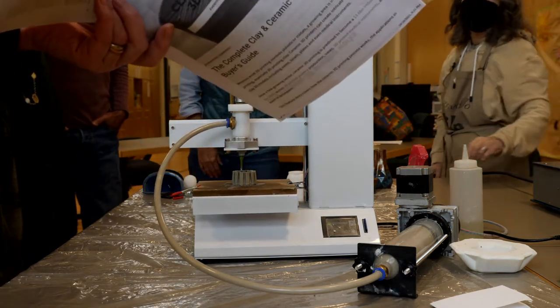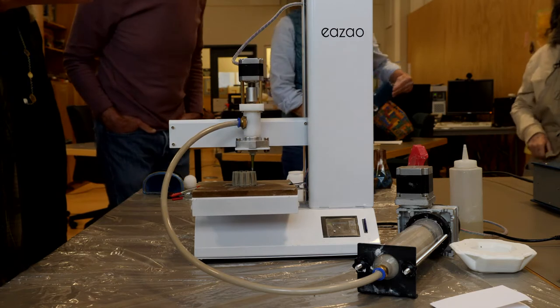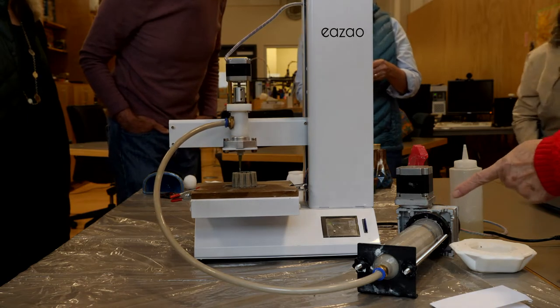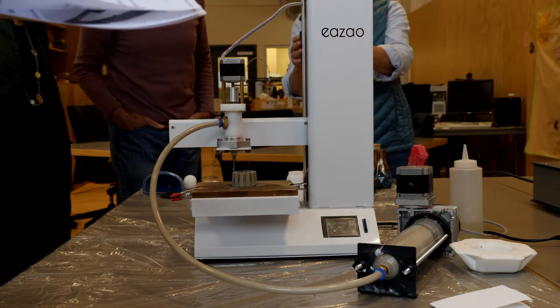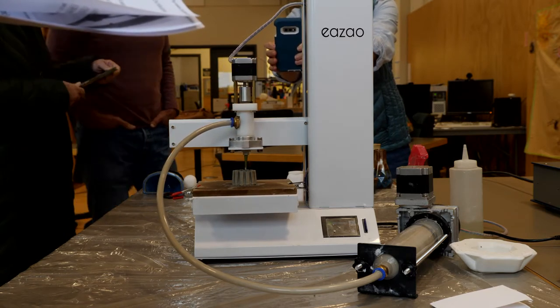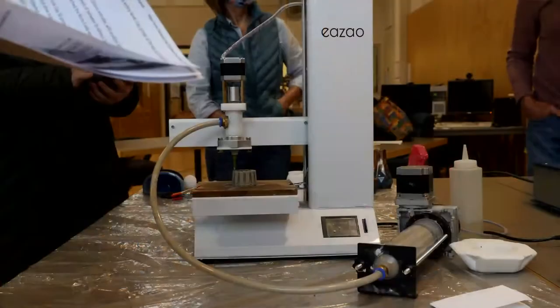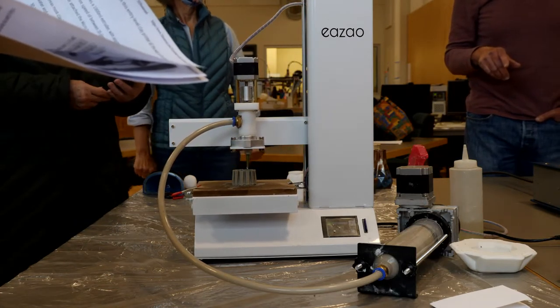So is this porcelain that you're extruding here? That is not porcelain. It's just stoneware. It's the most plastic stoneware they have. I can't remember the name. You don't buy the clay in tubes, right? It's just regular clay, and you pour in about 10 ounces of water in the bag of clay, or 15, they said. So you really get it super wet. And so you didn't make a slip, you just made your clay really slippery. That's what they said to do. Take a bag of clay, 25 pounds, pour in a pint of water. And then I took the very wettest part.